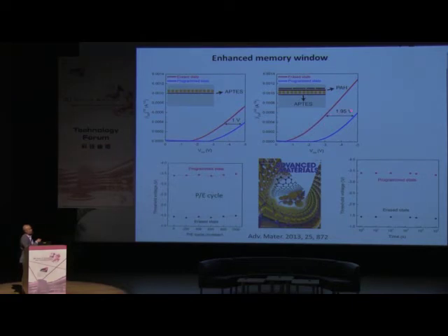So what is happening here is the nanoparticles, of course, trap their own charges, and in fact graphene is a kind of strange metal that we know also starts to trap charges. So you have two kinds of trapping layer. Plus, this graphene has a kind of smoothing effect, not allowing the particles to intrude into the semiconductor, so they completely fill up the surface. So both together work perfectly as a trapping center and also give a barrier for the charges not to leak back. So twice the retention time and twice the memory window enhanced.